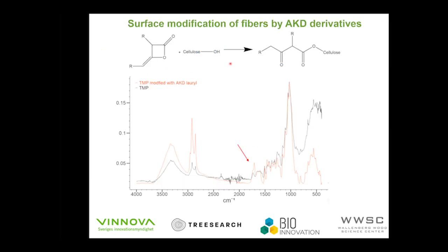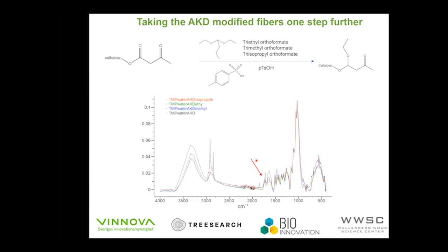Here you can see an example of the reaction. We have cellulose with an OH group, and there is a reaction between this OH group and the AKD. The AKD opens and gives us this product, which, because of the R chains, is more hydrophobic. The confirmation is from the IR peaks here. You can see these 2 peaks; they are the carbonyl peaks, which confirm that our reaction has worked.